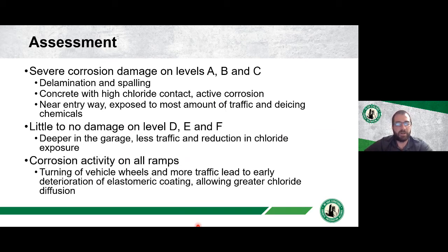Near the entryway where cars are coming in and out, that's obviously the most exposed. Levels D, E, and F were deeper in the garage, and so they had less exposure to traffic, and they had a reduction in chloride exposure. So D, E, and F had little damage. They were in really good shape because, by the time cars get down to that level, there are fewer cars down there. They've kind of deposited the moisture and chlorides on the upper levels.